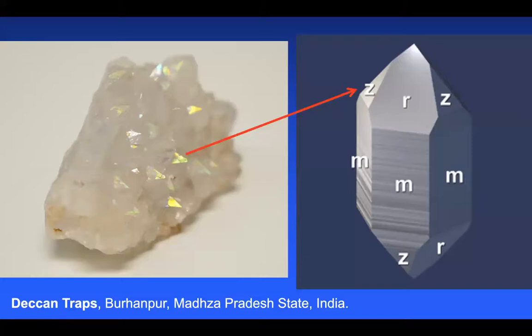And the way they grow is that basalts are extruded in this massive extrusive process that we don't completely understand. And as they cool, there's a lot of outgassing of water, carbon dioxide. The basalts actually harden and they trap these gas bubbles within the basalt. And then at a later stage, some silica-rich waters percolate through and begin to deposit quartz on the insides of these cavities. And so these quartz crystals are growing to the interior of the cavities.